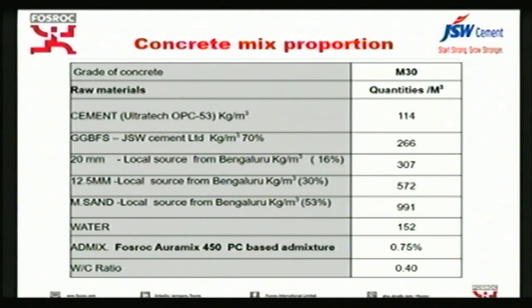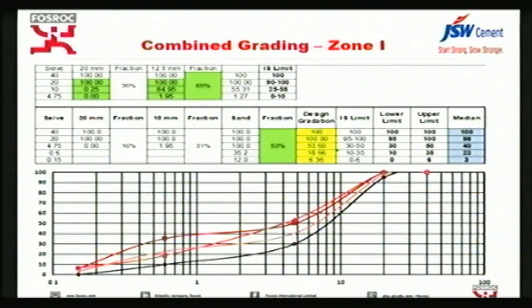The cement content is 114 kg per cubic meter, and GGBFS is 266, that is 30% OPC and 70% GGBS replacement. With 20 mm aggregate, sand is around 53%, and water cement ratio is 0.4. Admixture dosage varies from 0.6 to 0.75. Anyway, we'll just confirm with Nagesh what dosage was added there. So this is the analysis of the material being used there.